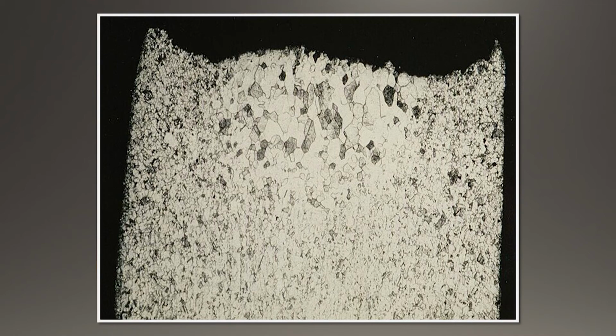Now, the break doesn't always occur in a rod. You might be able to draw 5, 6, even 10 dies down and subsequently get a wire break. And so the only way to tell would be to do something like this. Polish it, etch it, and see if you're seeing any subsurface duplex grains that are present.